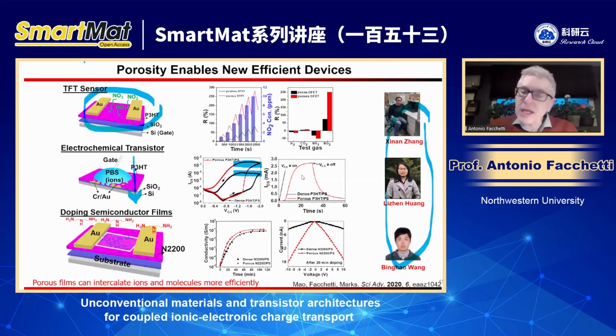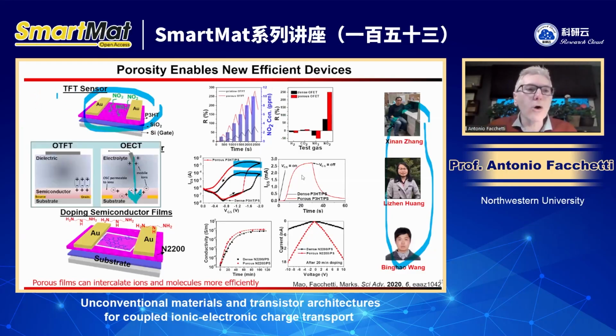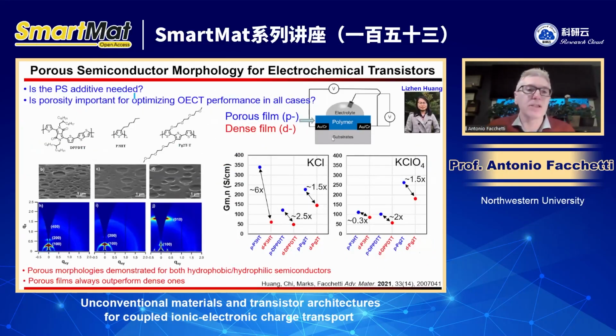So we showed that, we demonstrated that. We did also another step, which is we actually make holes without any polystyrene, because polystyrene is not an active material. And you see here that there are 3 polymers. Again, using breath figure, we can find conditions to create these holes into the semiconductor. And also another question is, can this porosity always be useful for OECT?